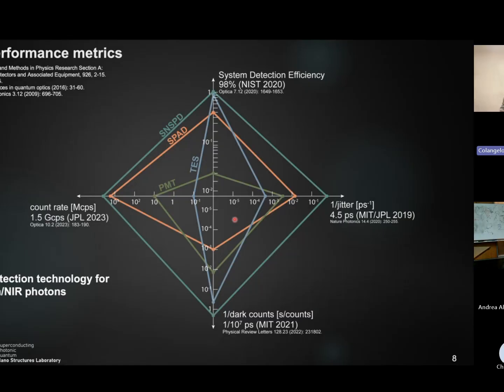The problem with this plot, something that I never mentioned, but the talk is about this, so it's important to mention, is that this is a lie. This plot gives the idea that the SNSPD can get in a single design all of these very high performances, but that's not really the case. So we do have trade-offs between all of these metrics, and there are some important trade-offs, for example, between the efficiency and the jitter, where we get a mediocre detector if we try to get in between. We can maximize for efficiency or jitter, but never both at the same time. And this is a problem because the new requirements for protocols do actually need this detector.